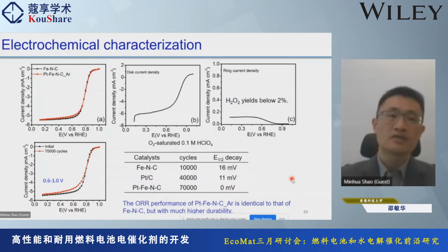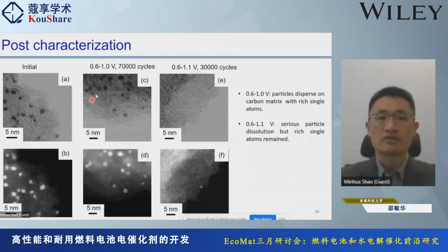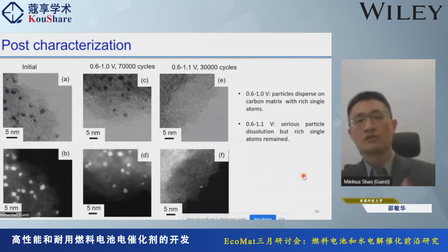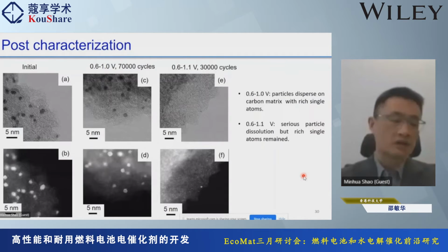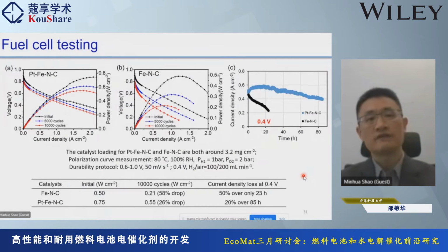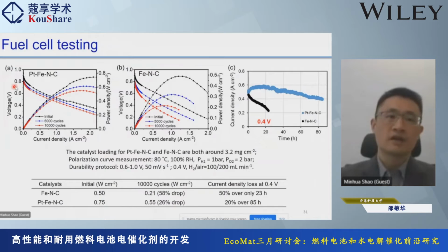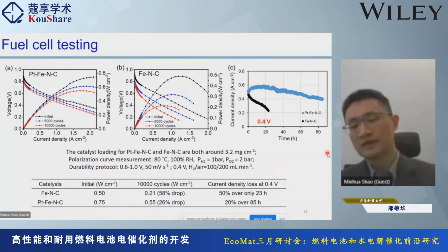Okay, and this is some of the post characterization after the cycling. Okay, so after 70,000 cycles, up to 1 volt, you can see the particles are still there, right? But if you go up to 1.1 volt, the majority of the particles are gone, but the single atoms are still there. You still see a lot of single atoms. Okay, so the dissolution mechanisms for the nanoparticles and the single atoms are totally different. Okay, so we also did some fuel cell testing. You can see that the platinum iron nitrogen actually has better durability than iron nitrogen. Okay, but this improvement is very limited.